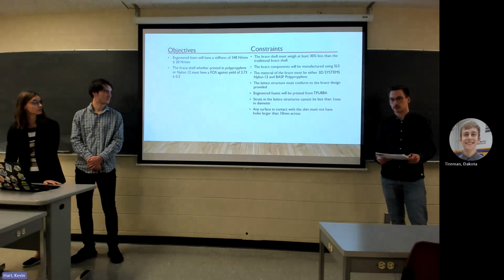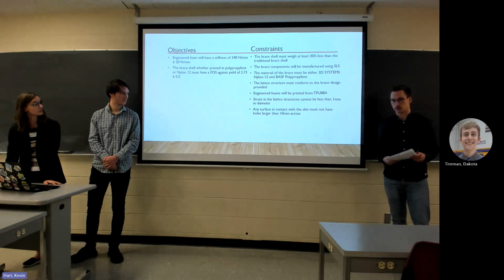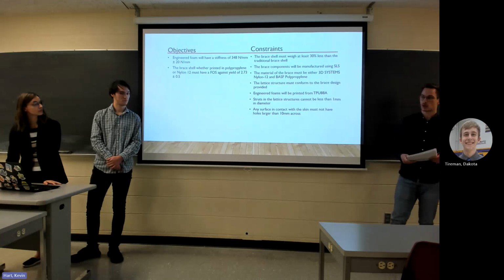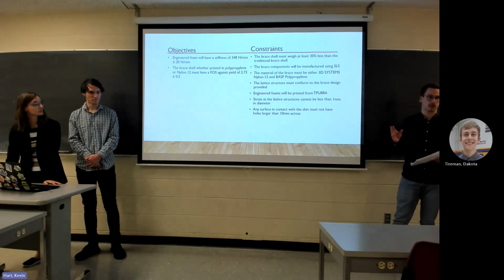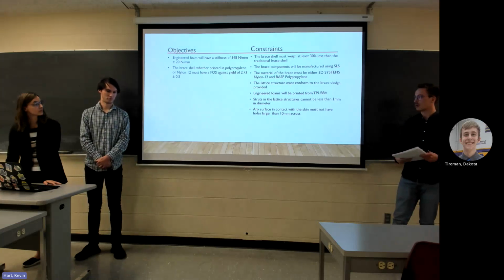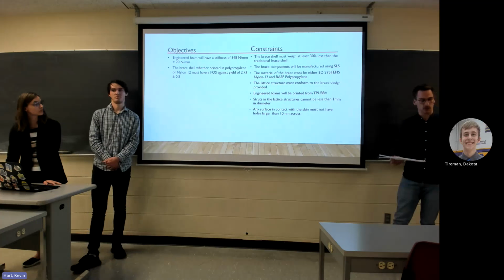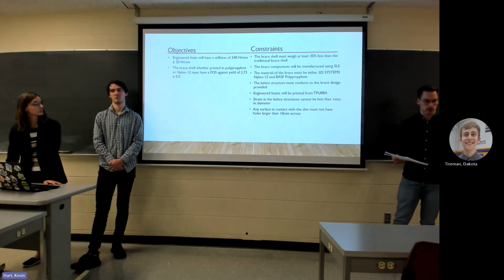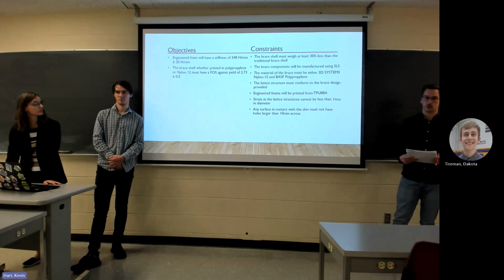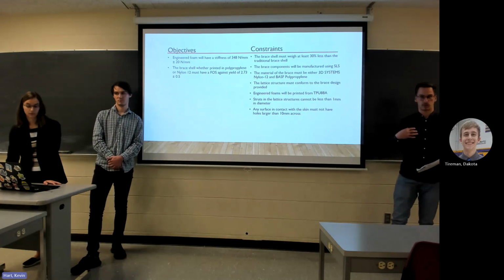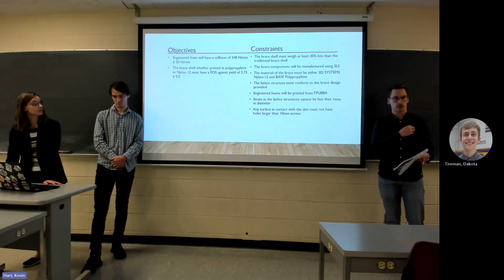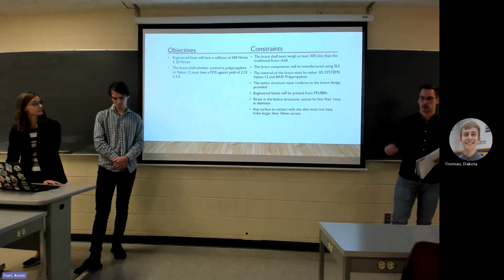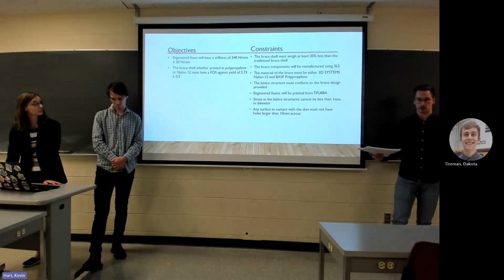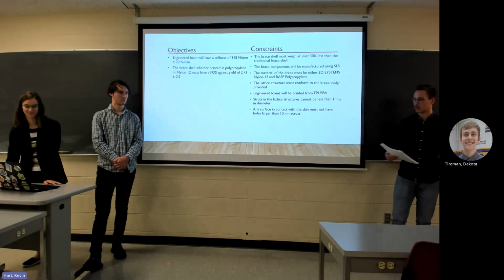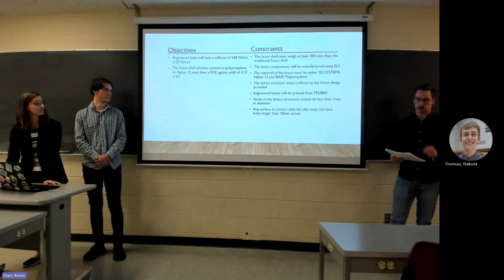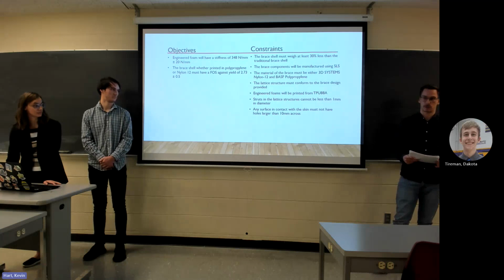And now a medical constraint, the holes that you see, especially in foam padding or any part of our brace that is going to touch the patient, can't be bigger than 10 millimeters. 10 millimeters is roughly like the diameter of this pen. Due to chafing on the skin, you wear it, you're moving it, and by having big openings that are touching your skin, you have rough chafing, which of course nobody wants to have. So we have to have holes in the lattice that are less than 10 millimeter diameter.